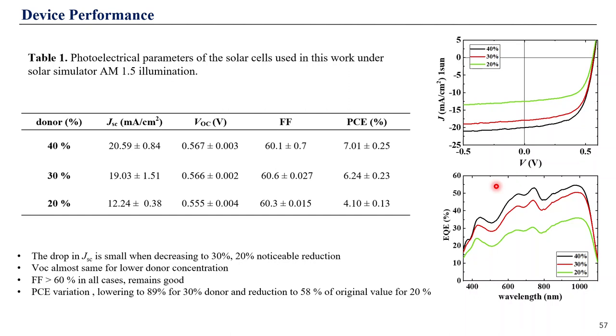reproducible and optimized opaque back electrode. So we didn't go for a semi-transparent electrode in order to have solid results without thinking about possible parasitic effects of unoptimized electrodes, and to be able to make a solid conclusion about device physics change due to dilution of the donor. So here we see that performance drops noticeably as we go from 40 to 20% donor concentration.